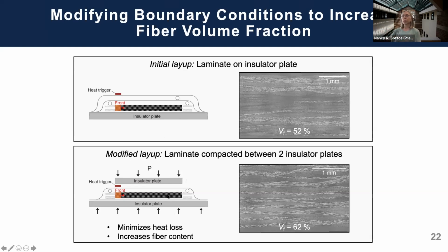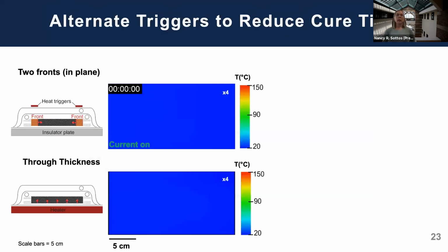And it does two things. It minimizes the heat losses and increases the fiber content. You see we get a nice 62% volume fraction composite shown here. So the compaction step works quite well and is quite helpful for producing high quality composites. You can imagine as parts scale and get larger, you're asking a lot for a front to propagate meters. And so we looked at different alternate triggers to reduce the cure time and also the distance that the front propagates.